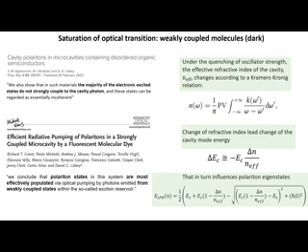Besides bright molecules, there are lots of so-called dark molecules, those molecules which are weakly coupled with the cavity mode. This always happens because some molecules have the wrong direction of their dipole moment with respect to the electromagnetic field. Some molecules are out of resonance because of the disordered nature of organic materials. This is very well known, studied in theory by Vladimir Agranovich, Maria Litinskaya, and David Lidzey, for instance, a while ago, and also experimentally in the group of David Lidzey. There are many reasons why dark molecules should be present in the system.